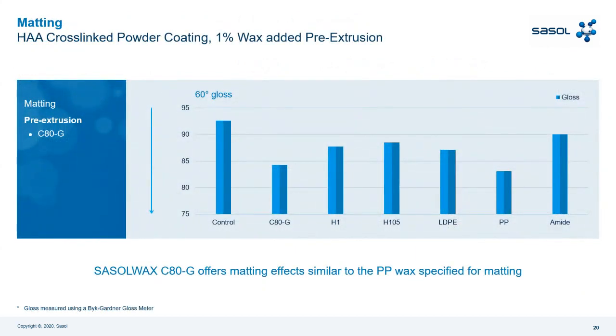Here are the first results. Matting with HAA cross-linked powder coating. You can have matting. You can see the control that has a very high value. In this case, you need to see the lowest value in the test. So with 1% of wax in pre-extrusion, Sasol wax C80G offers a matting effect similar to polypropylene wax. So you can see the C80 and polypropylene have a similar value.